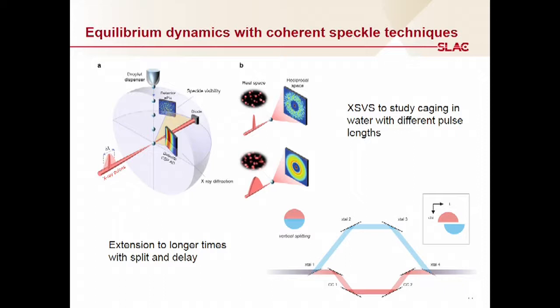So what they saw here was that they were looking at water. If you think about the classical Brownian motion picture, it has a ballistic regime and then a diffusive regime, and typically you see a smooth transition between those two. But what they actually saw was an intermediate regime that was not ballistic and not diffusive, which they, through theory, can explain with a caging mechanism in water. That means the hydrogen bonds in water create a kind of cage that inhibits the ballistic motion of these water particles. They saw that this existed over the sub 100 femtosecond time scale, which is a very new result that I think people had not thought about before.